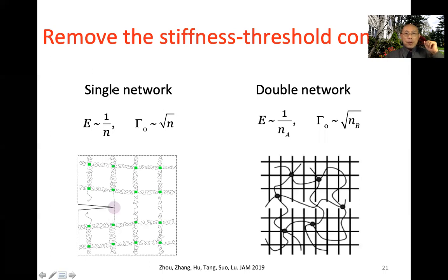So now, if you only have a single network hydrogel, I just told you there's a conflict. If you make the chain very, very long, fatigue threshold is great, but modulus is low. So you have a conflict. However, if you make a double network, you make polymer network A with short chains so that you have enormous modulus, and then you have another network, polymer network B, with very long chains, so you get high threshold. This double network will have both high modulus and high threshold. So it's both stiff and fatigue resistant.